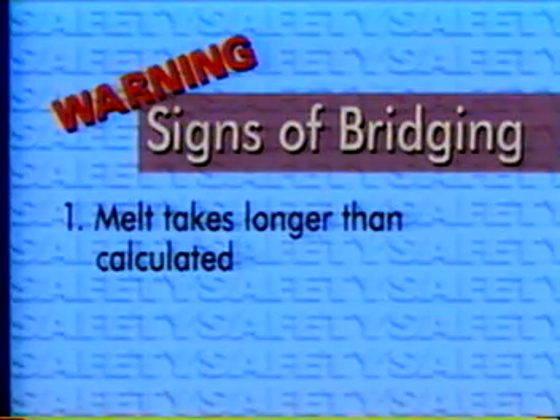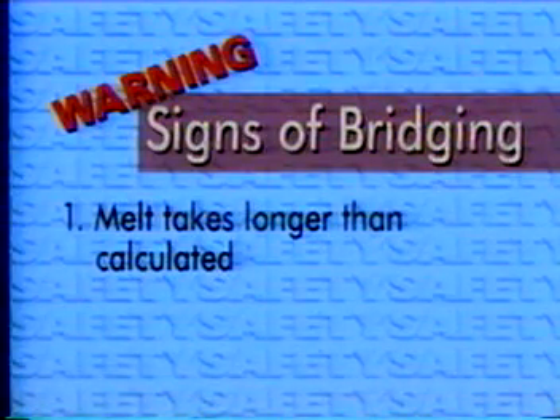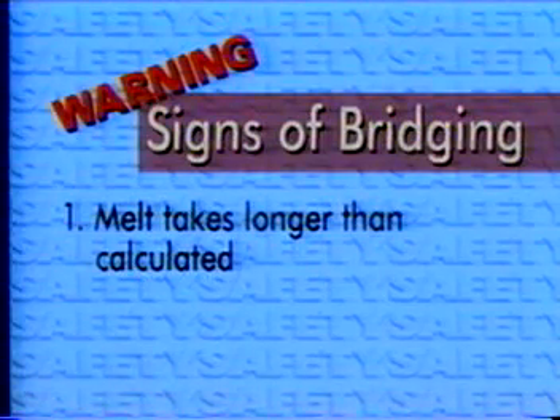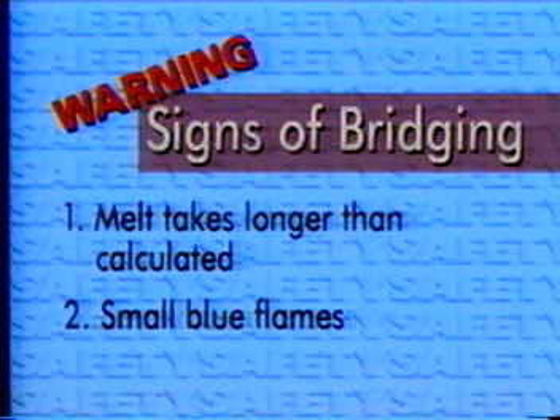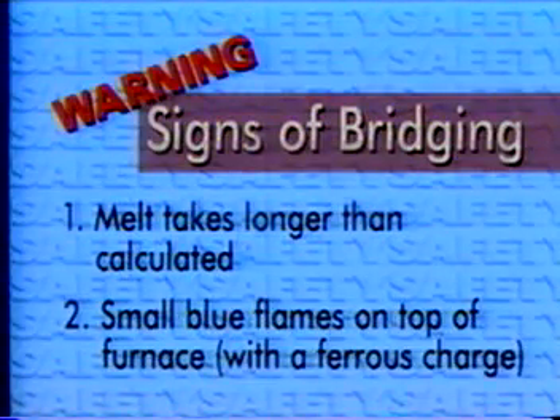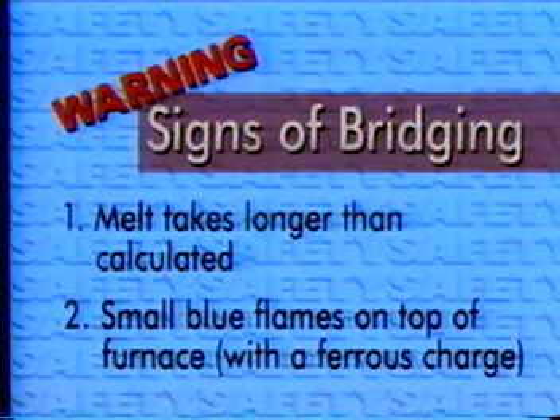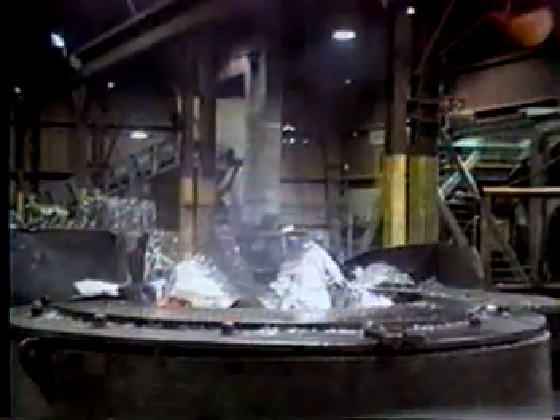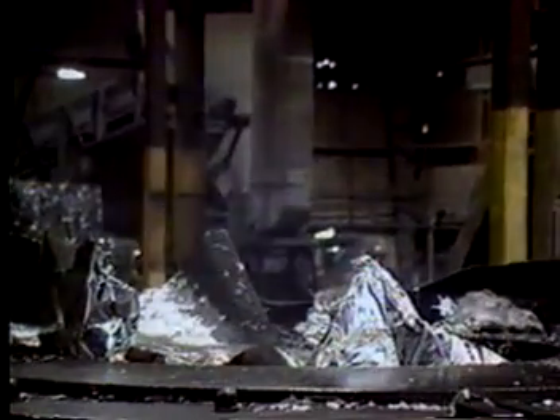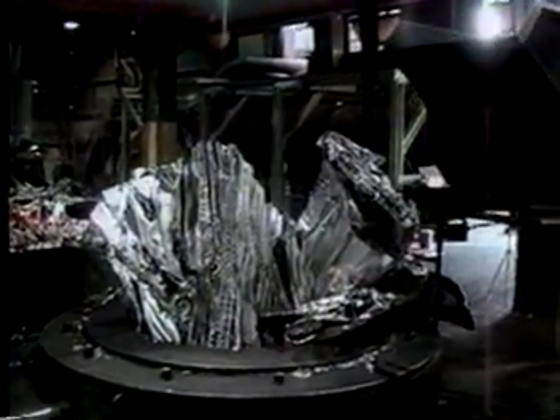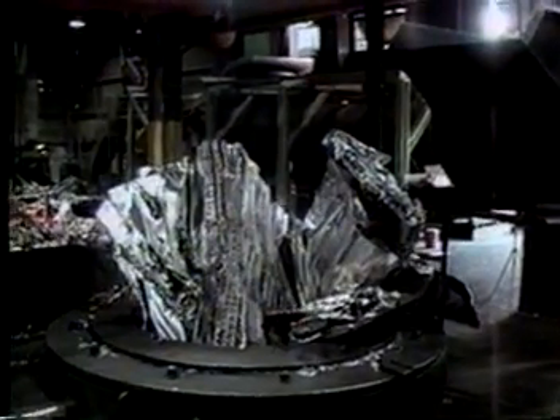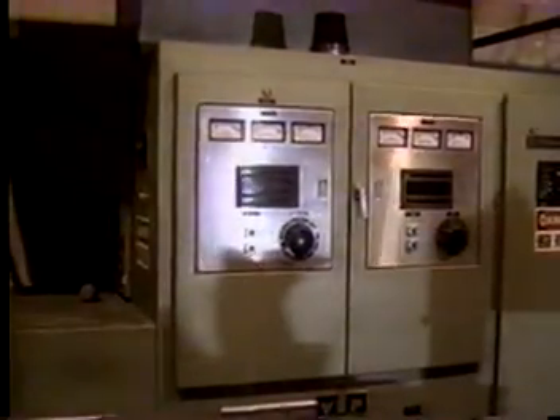If ferrous metal is being melted, the chemical reaction which it creates on contact with the furnace lining will, under superheated conditions, produce carbon monoxide. This gas may reveal itself as small blue flames on or in the bridge. The appearance of these flames indicates the bridge may be pressurized and it must not be breached. In the case of a non-ferrous charge, gas production will also occur, but there are no flames or other visible indications of its presence. If a bridge occurs, power must be turned off immediately until the bath temperature is known.